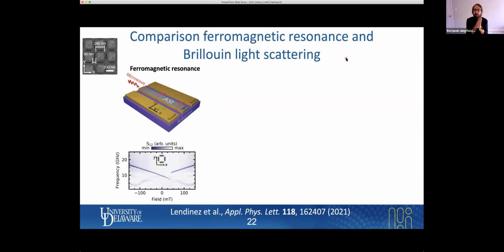However, as we now reduce the external field and approach zero field, the magnetization gradually rotates from the hard axis into the easy axis, which is aligned in the y direction. And remember, this y direction is parallel to the Ørsted field, and this means there is zero torque, and this is the reason why we don't see much of a signal over here in the low field regime. So bottom line here is, this resonance spectra doesn't give us the full picture. It's rather the technique that we use, but not the underlying magnetization dynamics that we see here.